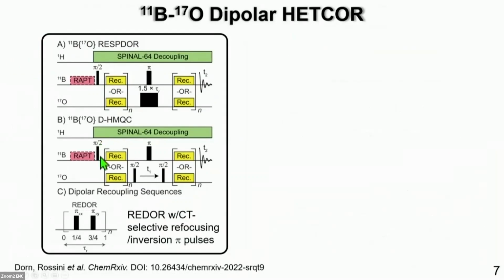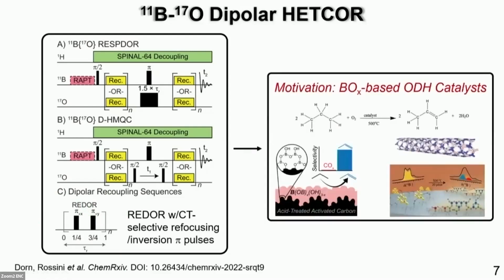And here, our recoupling sequence of choice is just simple rotational echo double resonance recoupling, where we are going to be using central transition selective pi pulses applied either to the boron or the oxygen spins. And we were motivated to perform these type of experiments because, as I'll show you towards the end of my talk, we can really utilize them to further determine structure within these boron oxide-based heterogeneous catalysts.